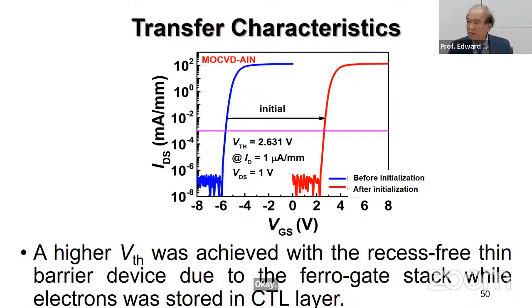And then after the device is fabricated on this epitaxial layer, you can see that the VTH has shifted to around positive 2.64, and all the others remain in good shape.